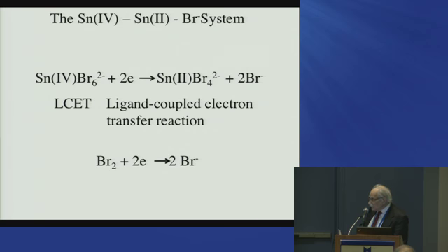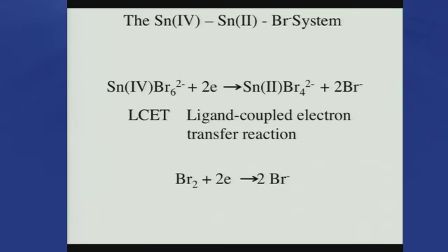It would be very nice to have a redox flow battery that has a 2-electron process because you immediately double the capacity. And this would be the negative electrode. Bromide-bromine would be the positive electrode. These can all be done in one medium without any membrane. And so, in fact, this is interesting but has problems as a redox flow battery.